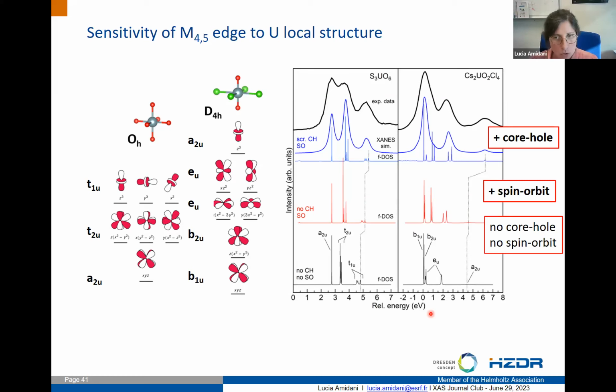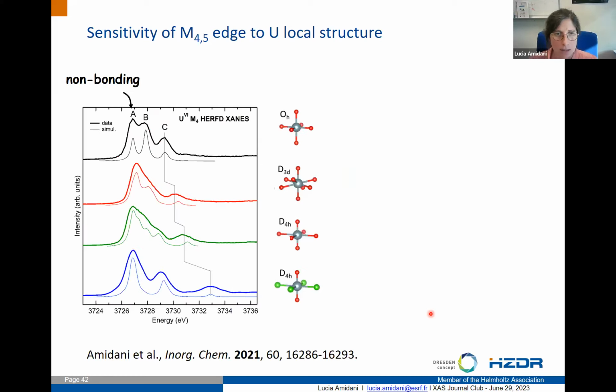And so actually, after this insight from the density of states, if we go back to our data, we can say, first of all, that our hypothesis was verified. The M4 edges of the uranium-6 clusters are very sensitive to the local structure. And what we can say is that in this series of elements, we found a sort of systematicity. The first peak A is always contributed by sort of non-bonding F orbitals, less involved in bonding.